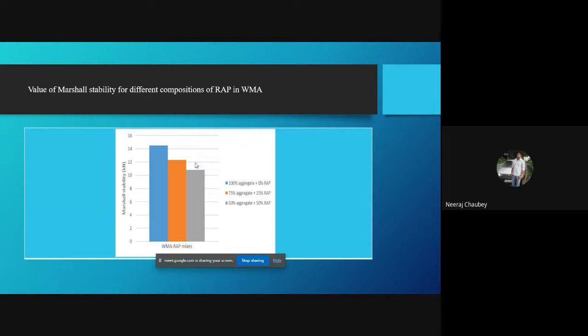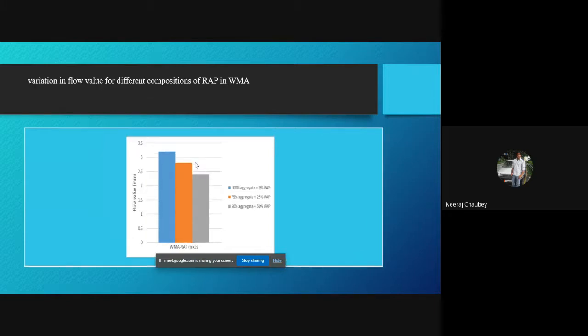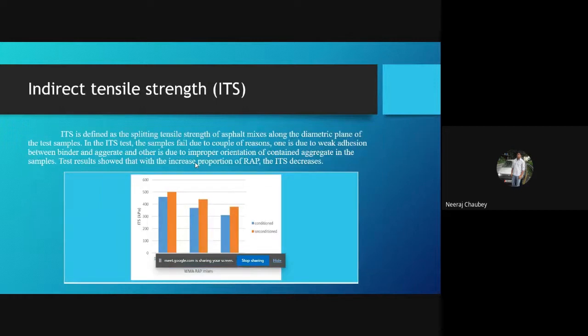The Marshall stability for different compositions of RAP in warm mix asphalt can be seen in the graph. For 100% aggregate it is maximum, and it reduces to a minimum at 50% aggregate and 50% RAP. These are the Marshall flow values obtained, also maximum at 100% aggregate and minimum at 50% aggregate and 50% RAP.